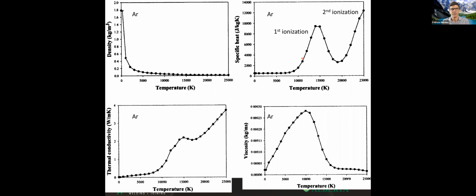And in the case of the arc, we have a similar thing. The phase transformation in this case is ionization, pure argon to argon ion plus an electron. And this hump here is associated with this first ionization. And then the specific heat goes back to be kind of normal and then goes back up again. Why? Goes back up again because it's now starting to lose a second electron at really high temperatures, right? Here what we see is the specific heat starts to climb to really high levels as we get the second ionization. Because welding is more or less 20,000 Kelvin, we seldom care about what is happening up here, but it's good to know.